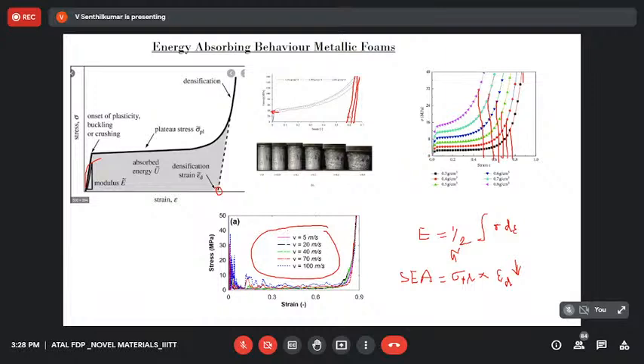So as it increases, you can see here, up to 100 meters per second, this is the curve for them. And there is not much variation in it. Compared to the steady state application of load, the impact load does not cause much variation. So finally, it is reported or concluded that you can design this energy absorption and design these dimensions simply using what? The steady state sustain values.